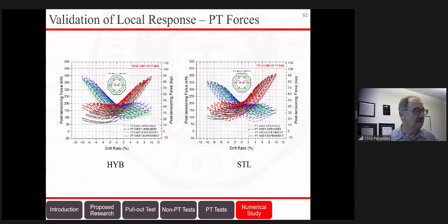So when I show this curve, you will see that the numerical model was close. On the left, first you can see that the blue and the red is the model, and the green and the black is actually the experiment. So they're very close, except for the pull cycles, the black seems to be a little bit off. This was the experiment. And as I mentioned, it's because there was a little gap, and that justifies that small difference there, where the bars, post-tensioning bars, were digging into the concrete. But overall, both models did not predict yielding, which is exactly what happened. So we feel that this justifies the model.